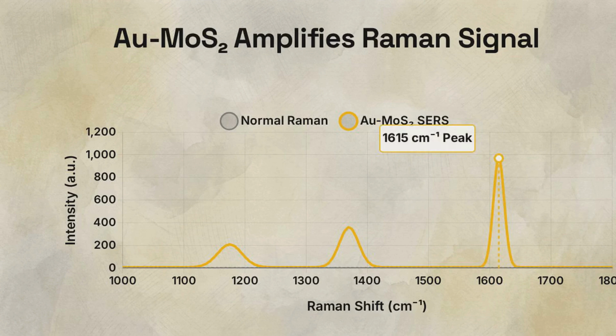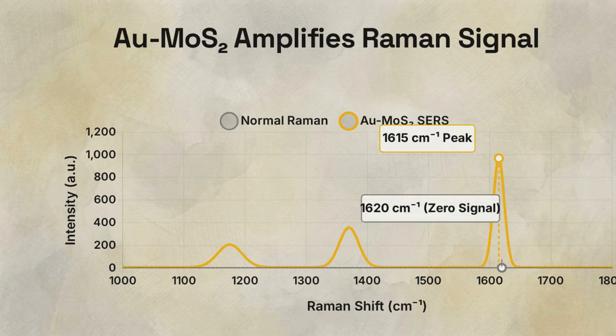Where the normal reading shows practically a flat line, the Au-MoS2 substrate forces massive, sharply defined intensity peaks out of the trace sample. The highest recorded characteristic peak for crystal violet appears right here, at approximately 1615 inverse centimeters. Directly below it, at roughly 1620 inverse centimeters, is where the normal Raman peak should be. The standard method detects almost zero signal intensity. Furthermore, researchers observed that even as they systematically decreased the concentration of the crystal violet drops, the hybrid substrate continued to yield a clear, highly detectable Raman signal.